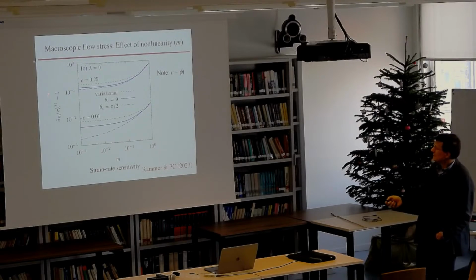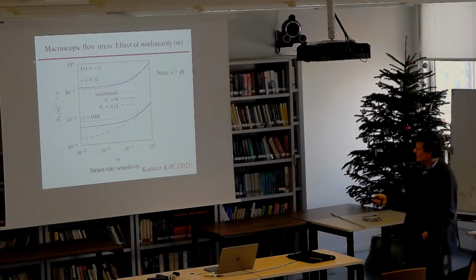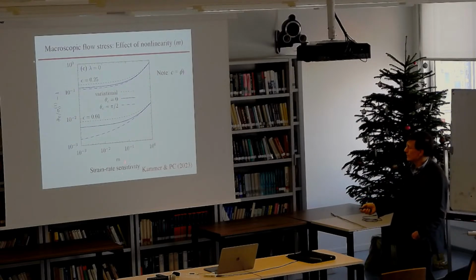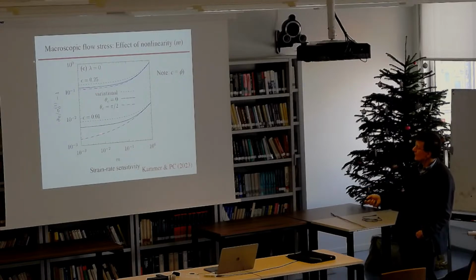This is the effective flow stress, which tells you the strengthening effect of the particles, as a function of the strain rate sensitivity. Here is 1, that's the linear case. As you go down, you go towards the ideally plastic limit. You see that the effective flow stress goes down with increasing nonlinearity. These are two different volume fractions.